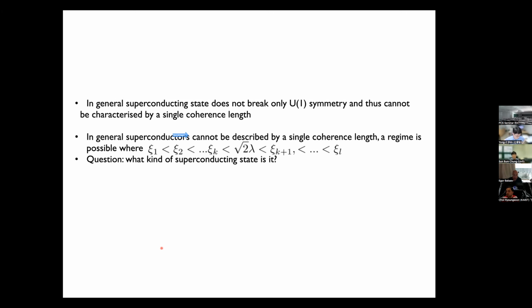In general you cannot have a dichotomic classification of superconductors. Let me make the first observation: in general the superconducting state breaks more than one symmetry, and by definition in general you don't have a single coherence length. So if we have multiple coherence lengths, for example from breaking multiple symmetries, then there must be a state where some of the coherence lengths are smaller and some are larger than the magnetic field penetration length. And then what kind of superconductivity is that?